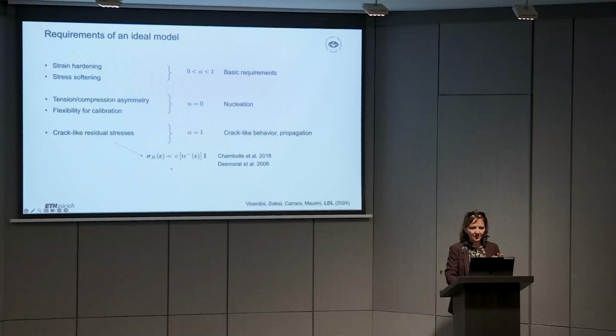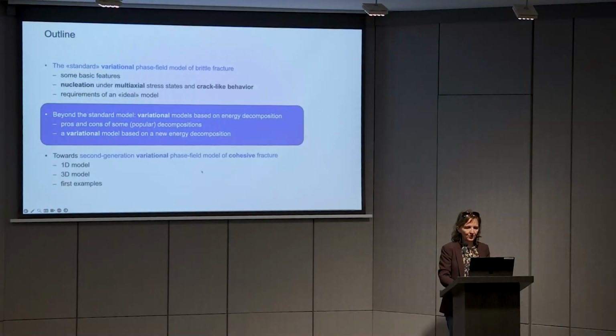This was nailed down by Chambolle and his co-authors in 2018, but there had been similar, although not variational, investigations done in the past in the damage mechanics community. So to have a good crack-like behavior, you want a residual stress of this type. So you want it to be proportional to the negative part of the trace of epsilon, yeah? And you want it to be isotropic. So this is a really important information coming from math.